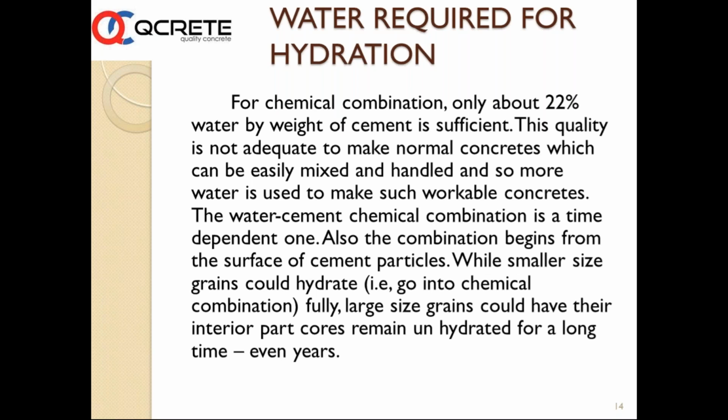One can have the interior core of the particle unhydrated even for years. They have looked at concretes of 5 to 25 years and analyzed them, and found that an amount of unhydrated cement continues to be part of the concrete in spite of time.